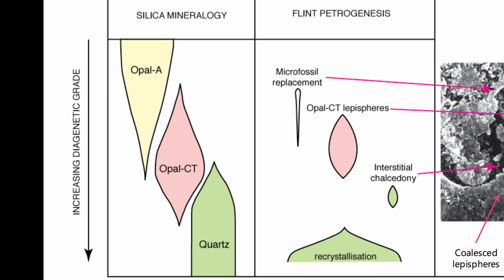in your hand. And with time, an increase in temperature, these things and various other bits eventually recrystallize to form the opal CT texture, such as I showed you previously. And then at a higher temperature, everything turns to quartz. It keeps the same structure, but it changes its chemical structure in terms of what's there. So all we find is normal quartz in most flints. If you go out to somewhere in, say, southern Limburg or parts of northern Belgium, you actually find some of the flints that are still made of this opal CT material. So we never got direct evidence that goes through that.